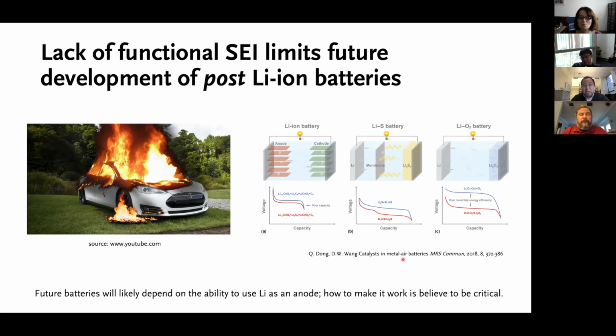So the bottom line, the take home message here, is that there is a lot of interest trying to enable lithium as a new anode material. It features the highest capacity. It features the lowest electrochemical potential. So why are we not using it? Well, this is because most electrolytes don't really form a good SEI with lithium. And then you're going to have problems like shown on the left-hand side. You don't want that to happen.